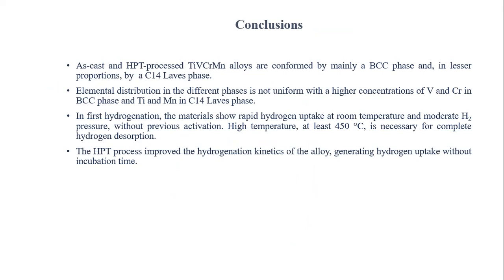Finally, conclusions. As-cast and HPT processed titanium, vanadium, chromium, manganese alloys are formed mainly by a BCC phase and in lesser proportions by a C14 Laves phase. The elemental distribution in the different phases is not uniform, with higher concentrations of vanadium and chromium in the BCC phase and titanium and manganese in the C14 Laves phase. In the first hydrogenation, the material showed a rapid hydrogenation uptake at room temperature and moderate hydrogen pressure without previous activation.